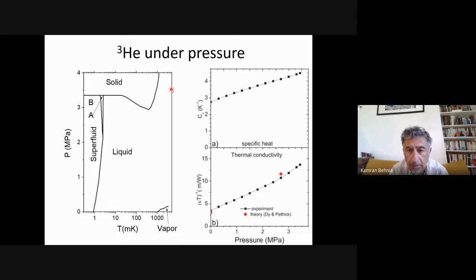Now, if I look at helium under pressure, this has been documented by Greywall's experiments. As you can see, specific heat is increasing. This is just because, you know, correlations are becoming stronger. This prefactor of the thermal T-square resistivity, which is kappa T divided by T, is also increasing because of this. And you see that actually the theory gives a fair account of this data.